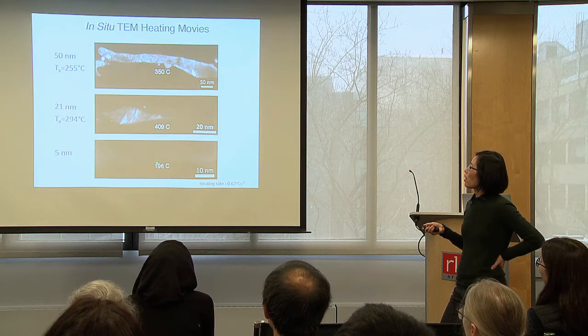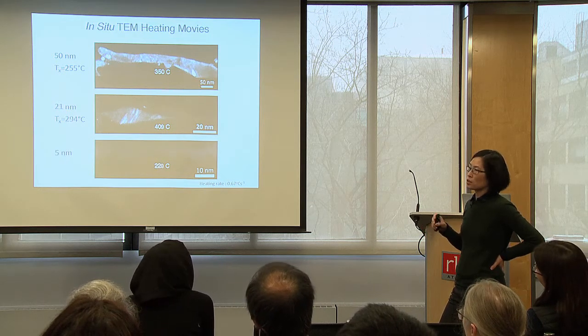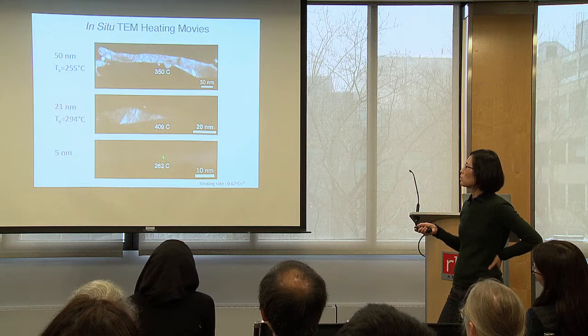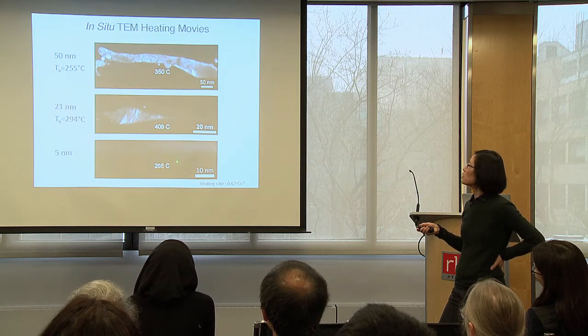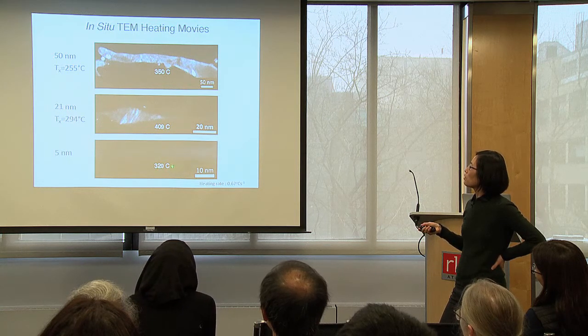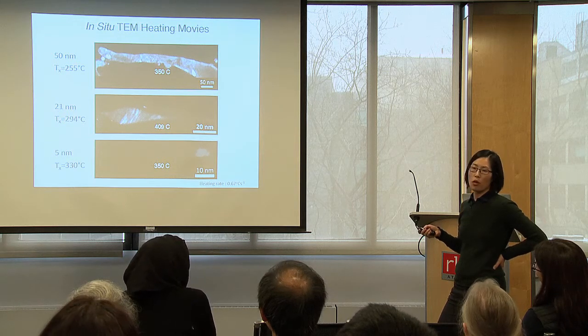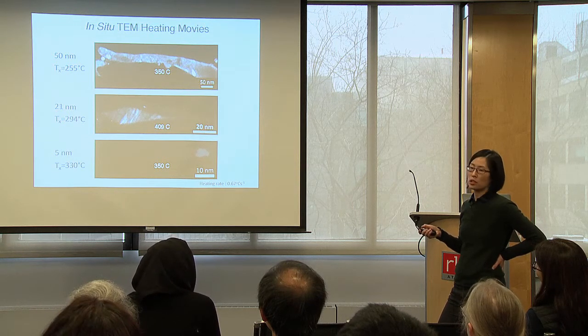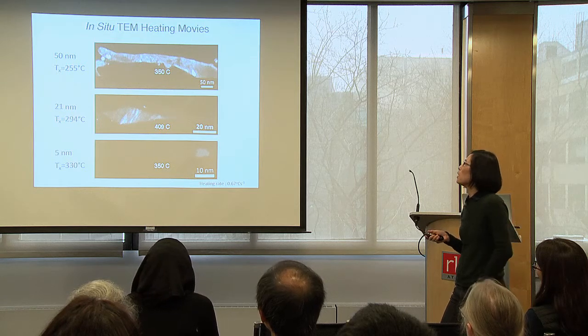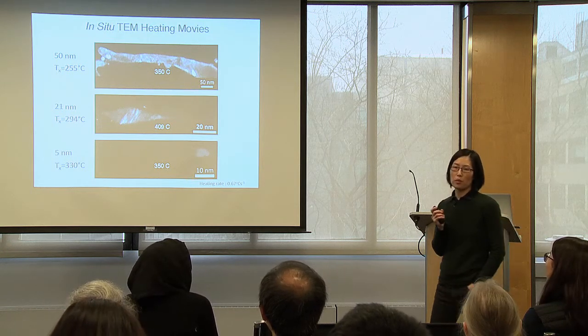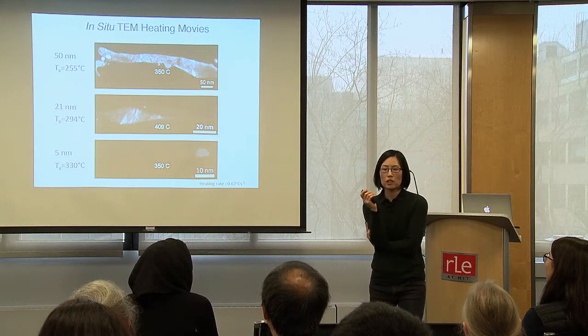Here's a 5 nanometer rod. We did some post alignment, but obviously we didn't do a good job. So here, it's over 300, it doesn't crystallize. Now 1 grain pops up, but it doesn't really grow, even though we're continuing to ramp up. So the crystallization temperature is all over the place. This is, again, the onset of crystallization temperature.